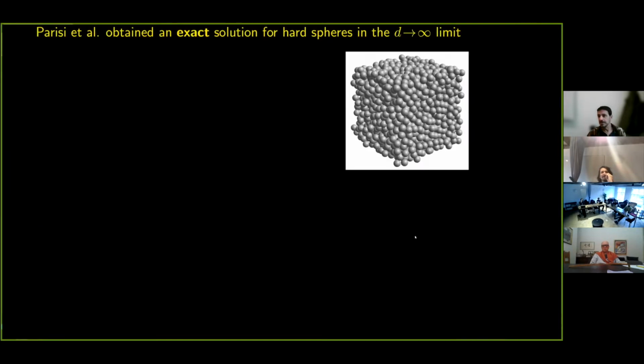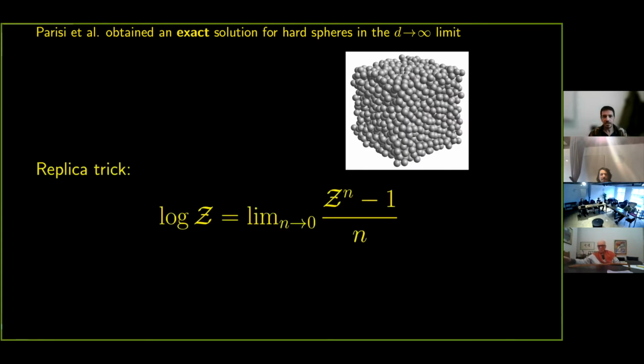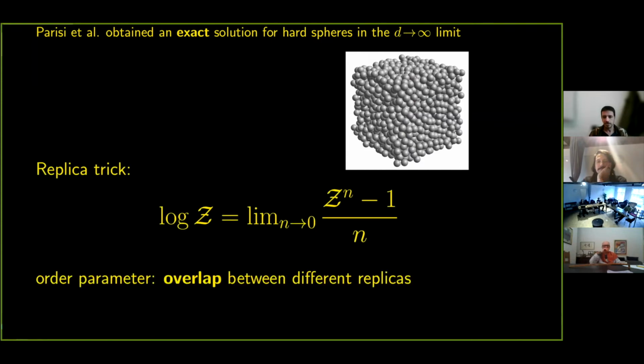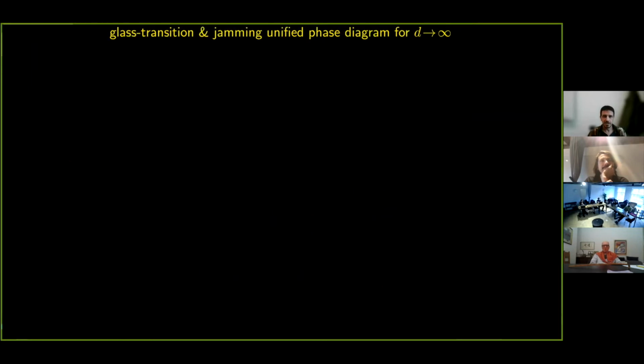Actually, in this work, they obtained the exact solution for the behavior of hard spheres in infinite dimensions. And this was done, as mentioned by John, using the replica trick, where the order parameter would be the overlap between different replicas of the system. I'm not going to go into the details of the calculation, but I want to show the results. The main result is a unified phase diagram, both for the glass transition and for jamming.